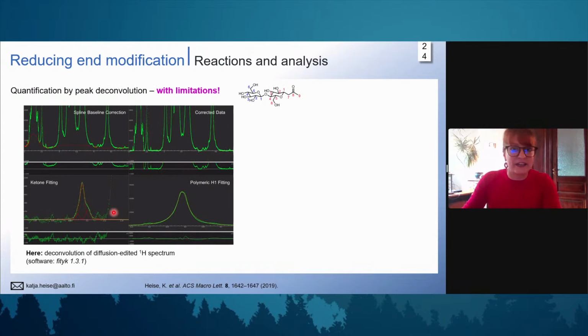And this is something, don't get confused with this image, it looks a bit complex. It's something we can do with a method, a FitYK, however, with limitations. So what we normally do to treat our spectrum, we do baseline correction, and then we select the necessary signals. In our case, we use the ratio of our polymeric C1 proton compared to the new keto functionality, and we deconvolute these signals and use the areas. This is something that could work, of course, for standard proton NMR spectroscopy.